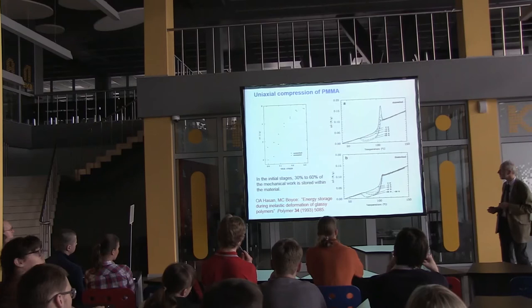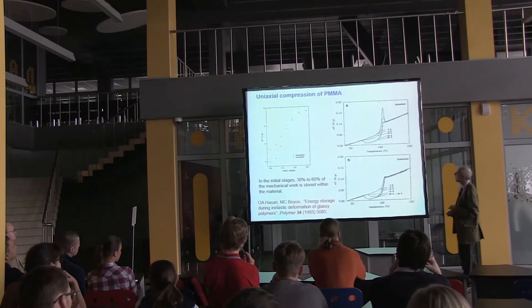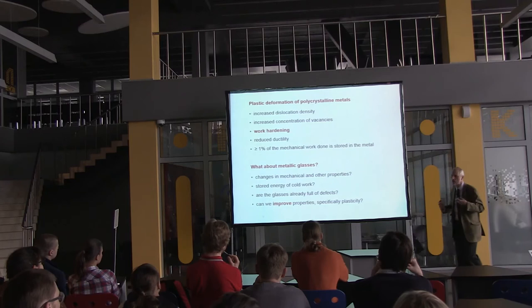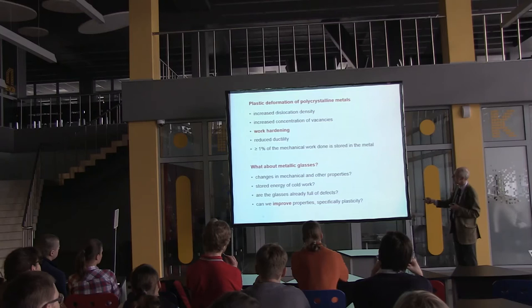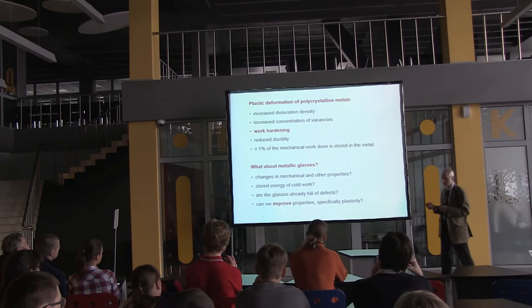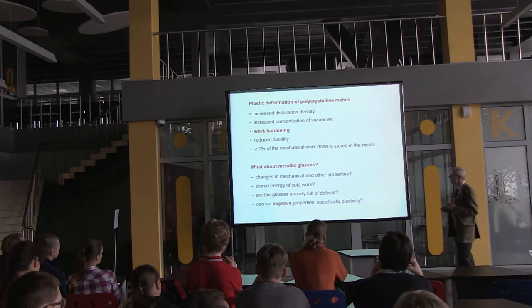The metals people in the audience will realize this is an unusually large number. For a polycrystalline metal, when you deform it you do work — you change the structure, produce more dislocations and vacancies and change the properties. But when you ask how much of that energy is stored, the answer is not much — typically of the order of one percent only, perhaps a few percent. So this is very different from the polymeric case of PMMA.